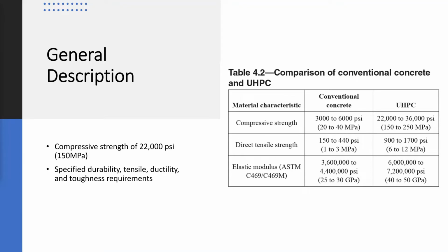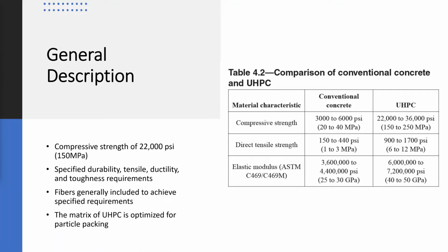The table lists the following characteristics: compressive strength, tensile strength, and the elastic modulus. With UHPC, fibers are generally included to achieve specified requirements. Also, the matrix of UHPC is optimized for particle packing, that is, the mixed proportions of typical components such as sand, silica fume, and cement that are optimized to achieve the densest packing possible.